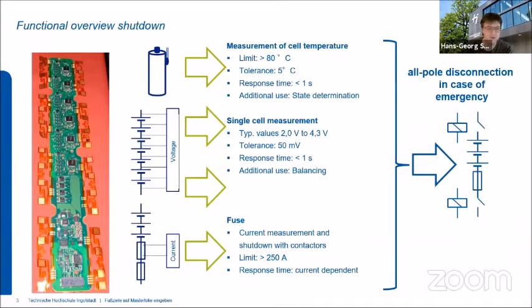For overcurrent, it's a little bit different, because a lithium-ion battery system can deliver lots of current. In vehicle applications, an EV system can deliver maybe 5 to 10,000 amps. So that's a huge current, and it can do a lot of harm in a very short period of time. Therefore, you must shut down the system much quicker than the 1 second mentioned for the other hazards. Here you have to react in the range of milliseconds, or a little bit longer if the current is smaller. Here you have to react rather quickly. And all these parameters are checked continuously by the BMS.